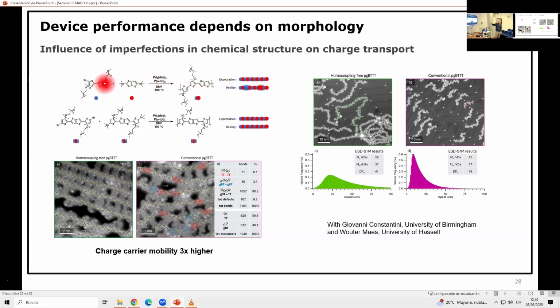There are several routes of making them. The more classical route, and if you buy this polymer, would be this way, which I can easily explain with the cartoon. You couple the red part with the blue part, and normally the red part alternates with the blue part, and that's also the most thermodynamically favorable. So you expect nicely alternating. In reality, you have these miscouplings. And actually, there are a lot of miscouplings.